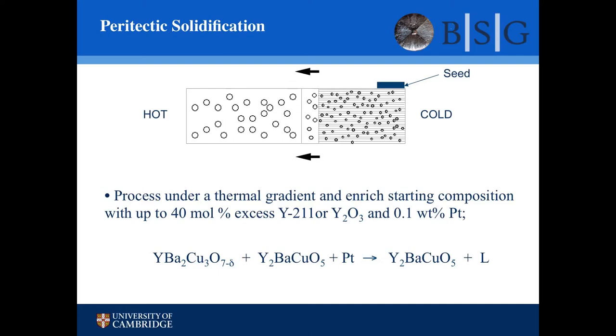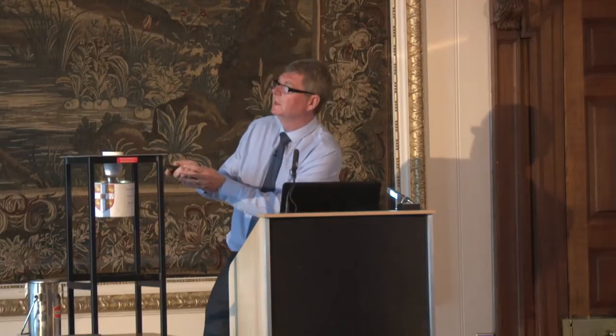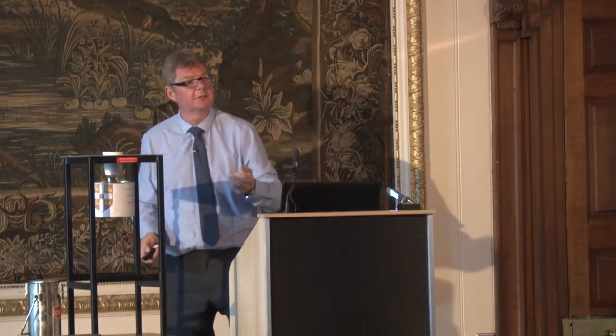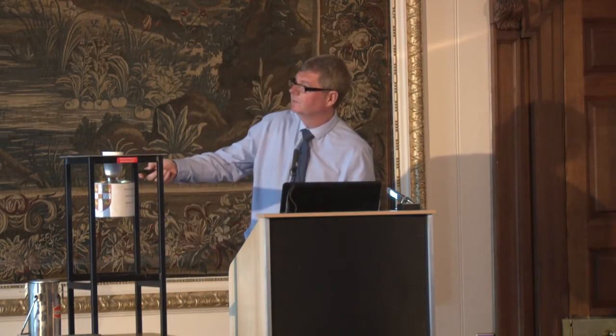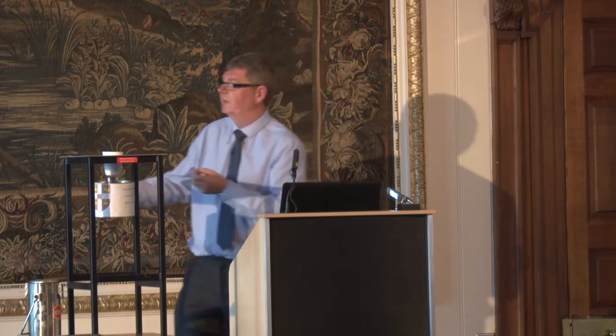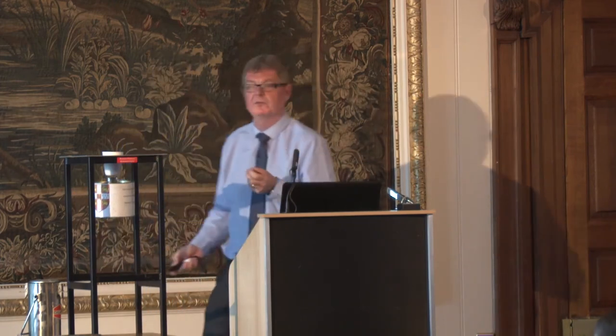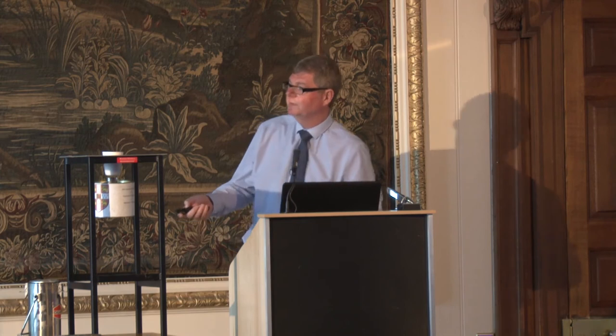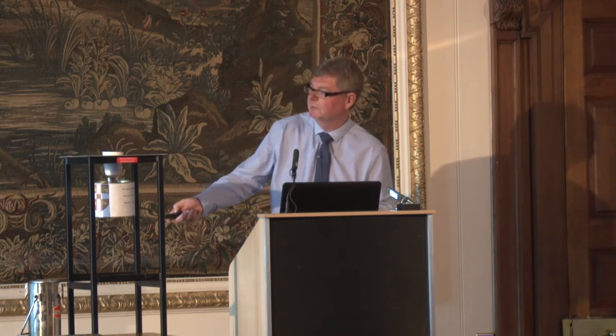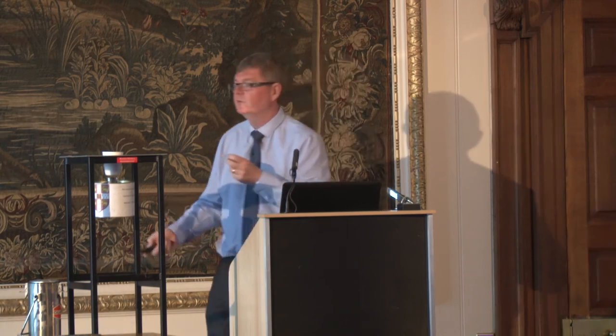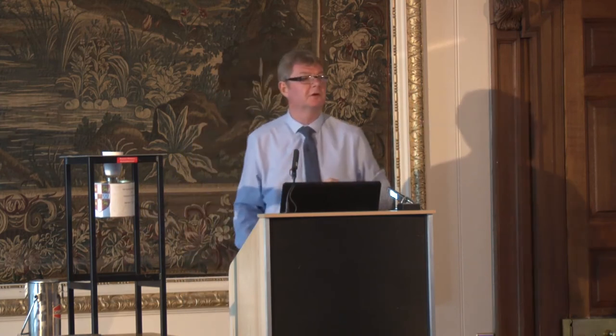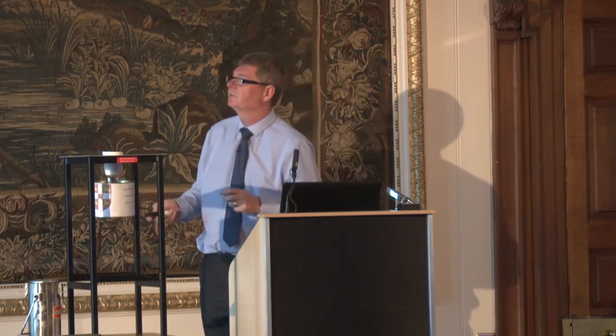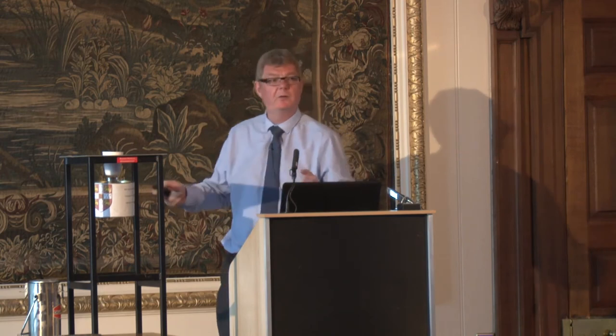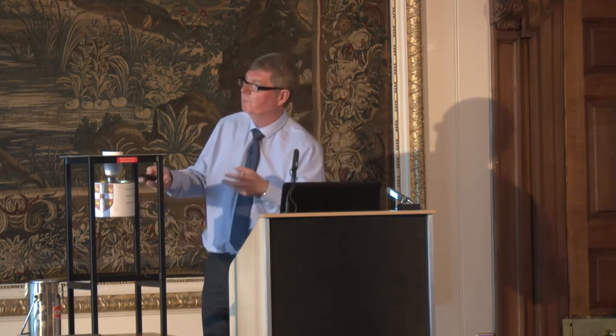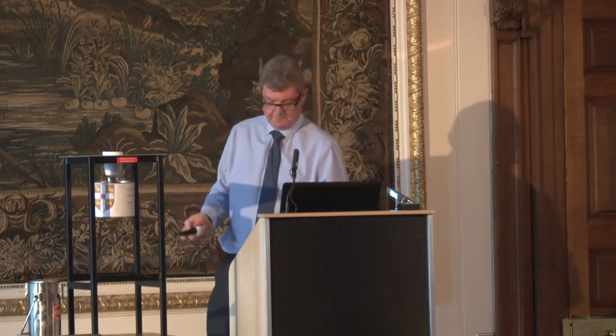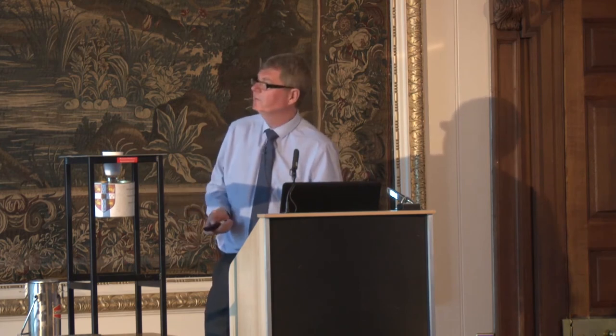So we've nucleated at the seed, the growth front's moving this way. If we're growing at a greater rate than we're dissolving, then we leave the 211 phase behind. So eventually we run out of rare earth ion and the thing stops growing. So we've got this very neat trick where we enrich our material with additional 211 before we start to grow. And that means we can grow bigger samples and we can grow for longer because we've got more solid there to mop up the liquid. So that's how we make single grain materials.